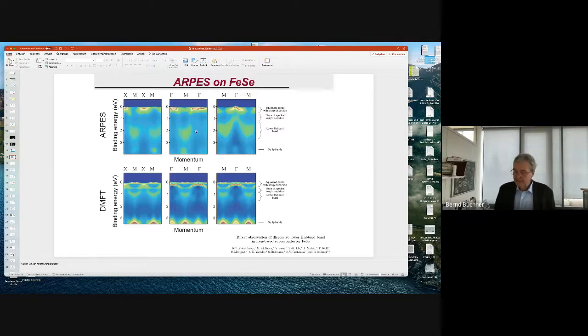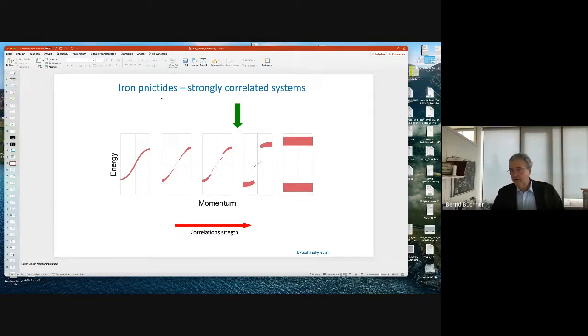So the message is, yes, band structure is correct. We definitely have these electronic states at the Fermi energy. However, we also clearly see these features which we expect in strongly correlated systems. So in some sense, our iron pnictides or iron selenides are located somewhere in between. Not very simple metals, also not clearly Mott insulators, somewhere in between, where we still see these features of the Mott Hubbard insulator, so this lower Hubbard band, and we see a renormalization, so the band structure itself changes, so the bands become flatter, the systems become heavier, a name which you also know from heavy fermions. So that's also a feature of these correlations.